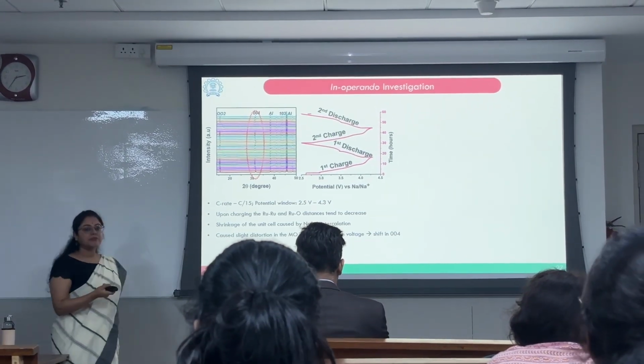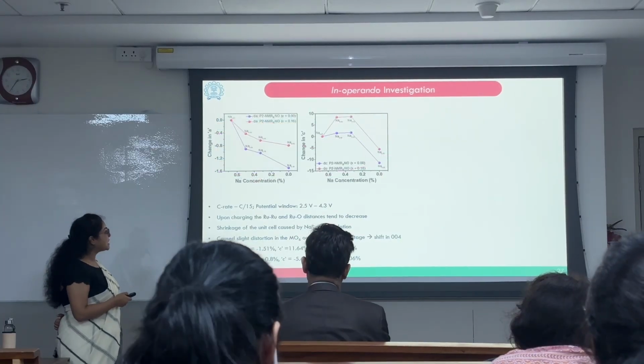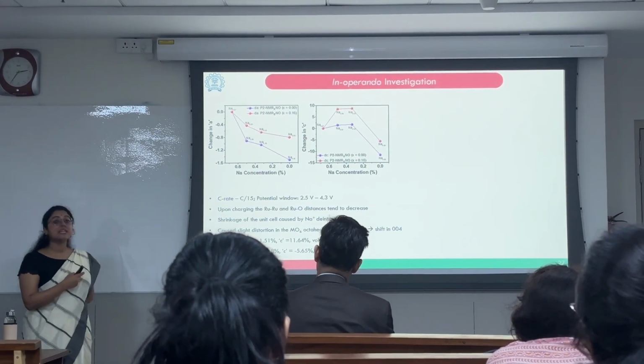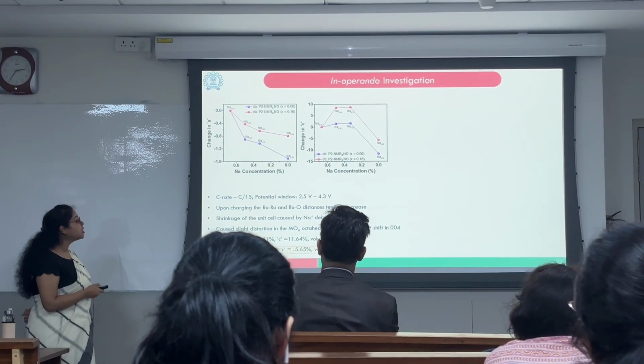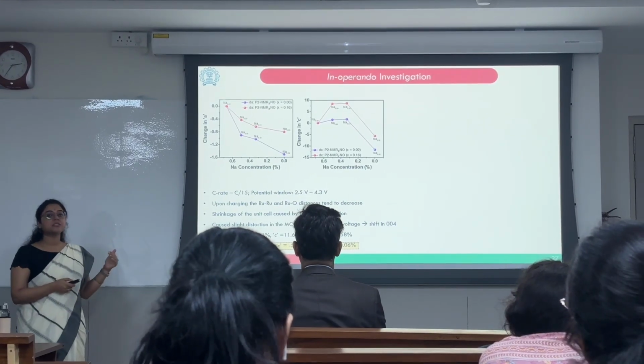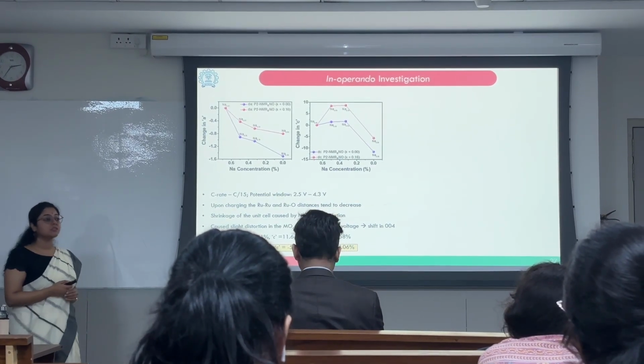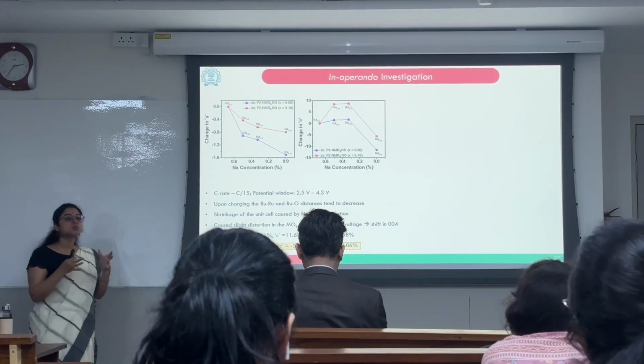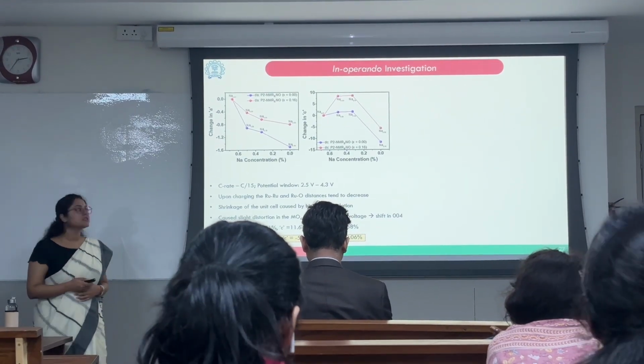So we also verified it through the lattice parameter changes and observed that the change in the a and the change in the c parameter was much smaller in comparison to that of the pristine cathode material, which suggests again that the ruthenium is able to stabilize the entire structure.